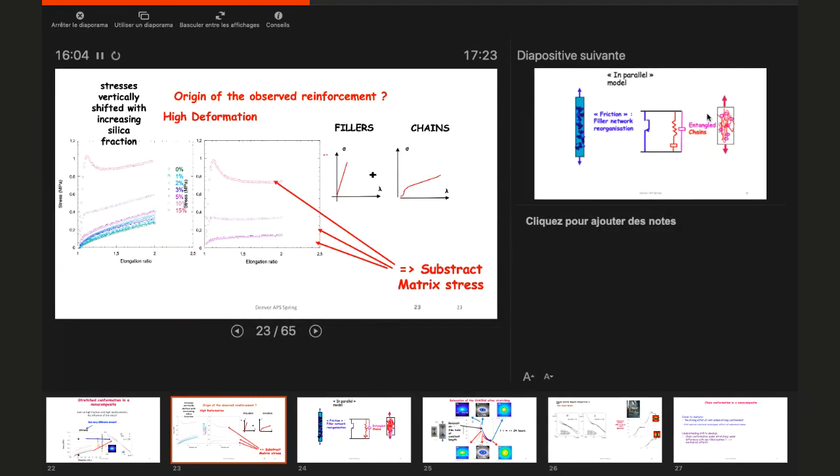What I was thinking is that I will send you this paper where we did the large amplitude oscillatory shear. This is polystyrene, grafted silica, and polystyrene above Tg. Basically the clusters break up as you deform. So you can see them by electron microscopy? Yeah. It's very, very dramatic.